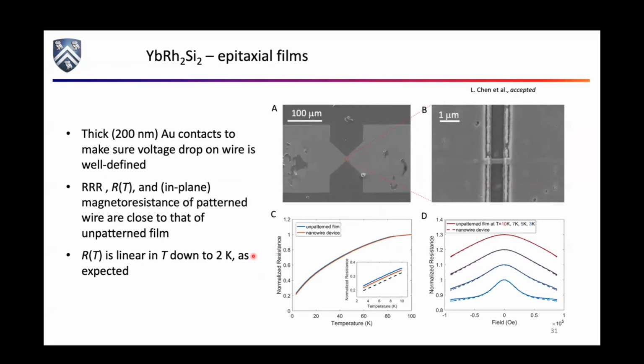What I want you to take away from this is the key here is we're comparing resistance versus temperature for the unpatterned film and the nanowire device, and they basically fall on top of each other. These have been normalized to take care of the fact that the residual resistance actually does go up when you pattern the film because you're basically making the thing more disordered. But if you normalize things at say 100 Kelvin and look, they really are on top of each other at low temperatures. They really do look linear in T. This dashed line is sort of your guide to the eye.